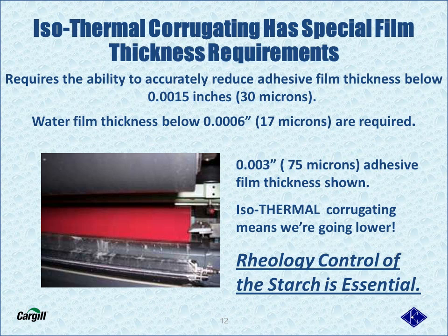Isothermal corrugating has specific adhesive film thickness requirements. Let's take a look at an isobar glue machine where we've got a 3,000th or 75 micron film thickness of starch on the roll. It's almost translucent because it's so thin. Isothermal corrugating allows us to use these kinds of film thicknesses because we change the flow characteristics of the adhesive with the addition of Cargill's Fast Break rheology modifier. Without Fast Break, adhesive film thicknesses lower than this are not possible because of the physical and chemical limitations.